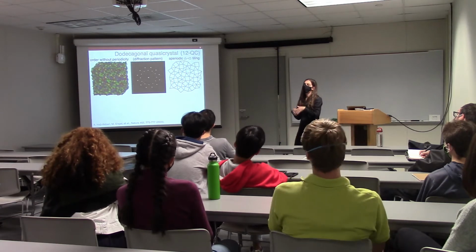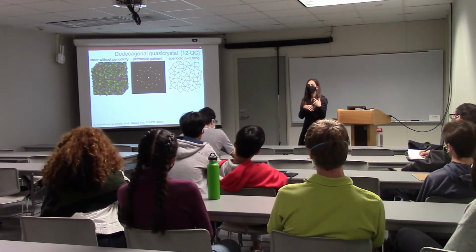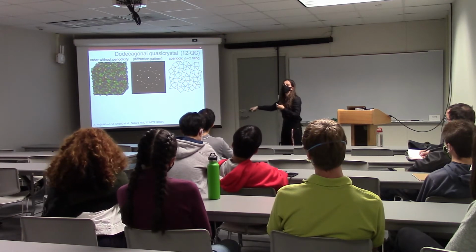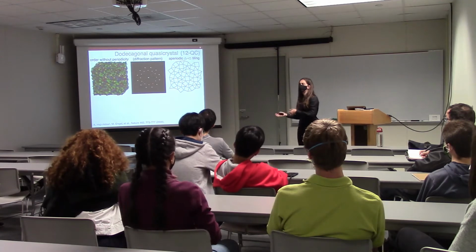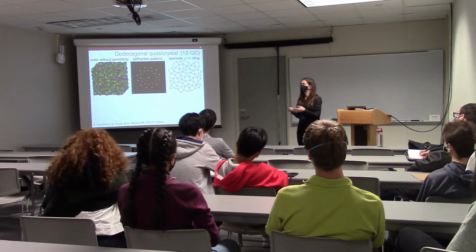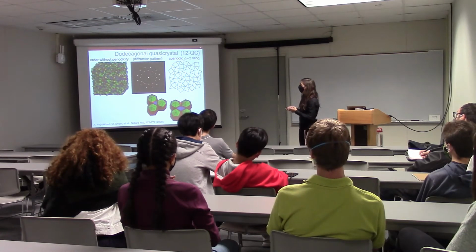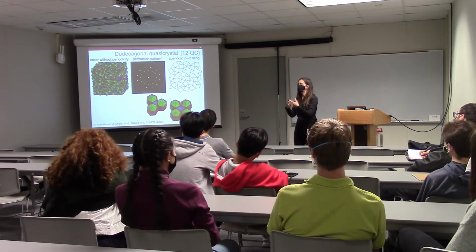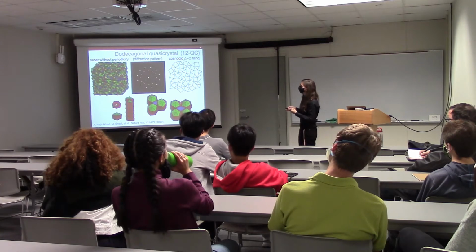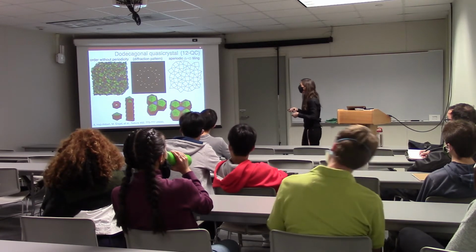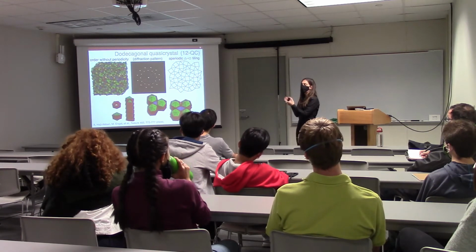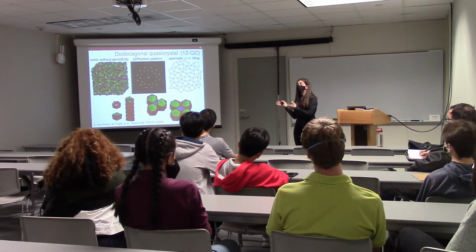The quasicrystal researchers that have been dealing with metals for a while came into the field through these kinds of studies, where suddenly in soft matter and in these coarse-grained simulations, where they didn't expect to see anything super complicated, they started seeing quasicrystals. This is approximately what the motifs look like if you color the tetrahedra accordingly. You have these columns of little pentagonal-like pyramids, hexagonal rings of dimers, and then they pattern these triangles and squares in this tiling to form this really complicated structure. And that's just the simplest shape, right?